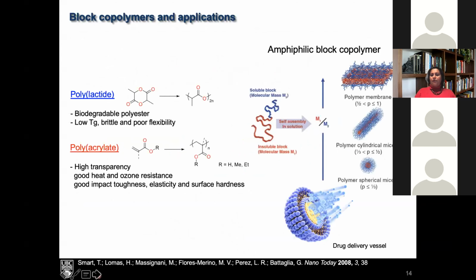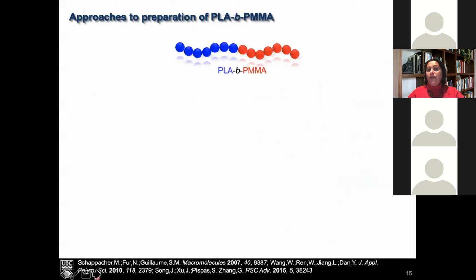And if we were able to generate block copolymers of this material, we're hoping to generate amphiphilic polymers that would allow us to start looking at self-assembly and start looking at larger, more organized structures in solution. And that's what you would be able to get if you can get controlled amphiphilic blocks, which we could in this case with acrylates and PLA. So how do you make these? So this is PLA block polymethyl methacrylate in this case.